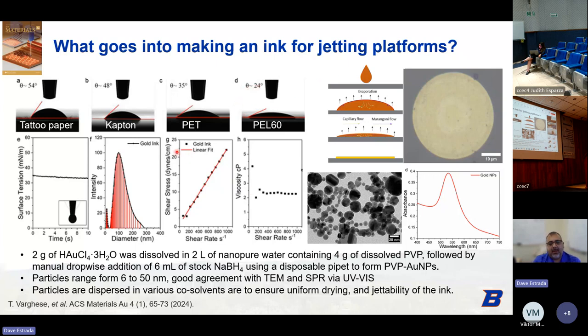So the next few slides show an example of what we've done recently with gold nanoparticles towards this process. For generating a gold ink, which has been shown to be compatible with these three different printers, we start with 2 grams of hydrogen tetrachloroaurate hydrate, mixed into nanopure water, which contains about 4 grams of polyvinylpyrrolidone as a surfactant or capping agent. And then we manually drop in about 6 milliliters of sodium borohydride as a reducing agent to pull the gold out of this precursor.